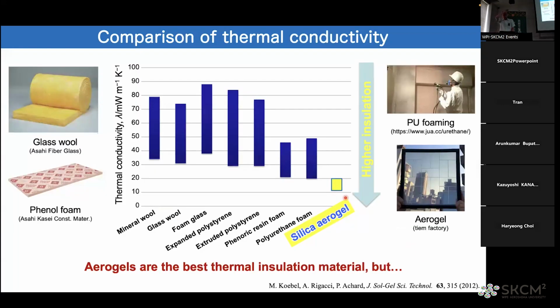So this is why people are interested in aerogels. This is one reason. They have very low thermal conductivity. These blue lines are the thermal conductivity values of the common thermal insulators like glass wools and the polymer foams. And you can see here, silica aerogel typically has a thermal conductivity lower than those common thermal insulation materials. The value is somewhere between 10 to 20 milliwatts per meter per Kelvin.